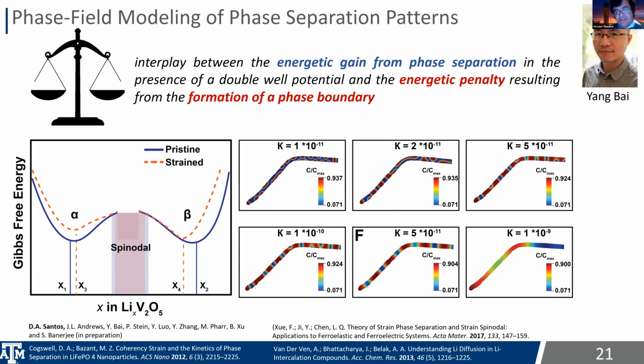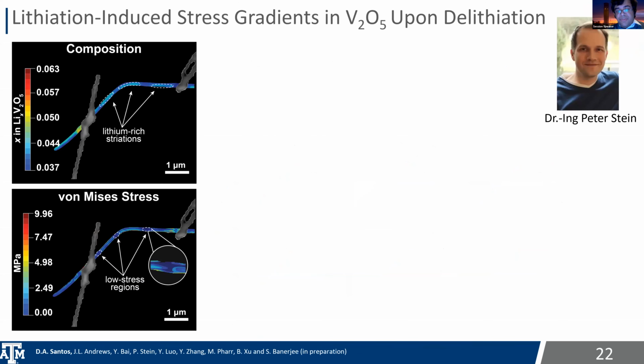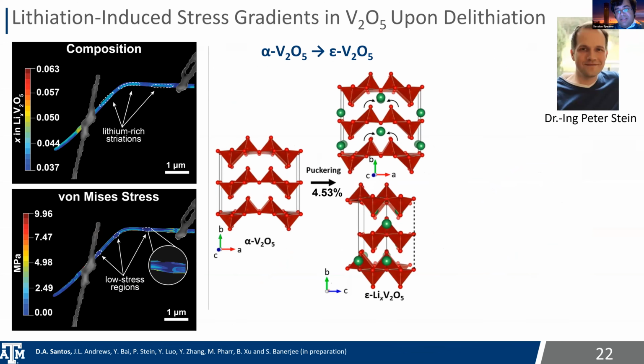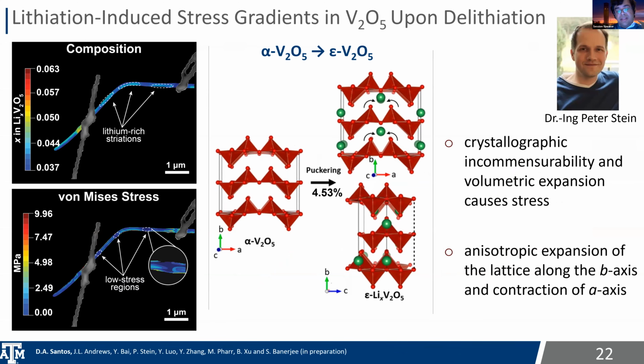So beyond the cool idea of seeing phase separation so vividly, as you can see in these images, and the computational phase separation, there are other implications. Of course, at each of these phase boundaries, you have some lattice mismatch, and this lattice incommensurability gives rise to these stresses. And we're just plotting von Mises stresses here because the orientations aren't entirely clear. But in principle, of course, we can plot directional stresses and analyze those as well, and we have in some more recent systems. The buildup of stress changes the diffusion directionality and diffusion rate in these structures. The buildup of stress in turn then changes further the specific heterogeneities that are formed in these systems.